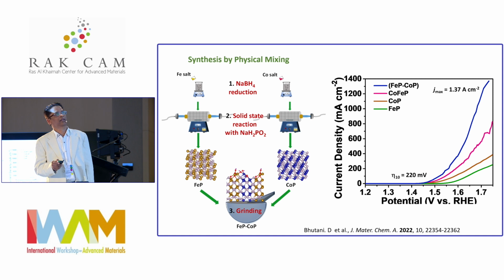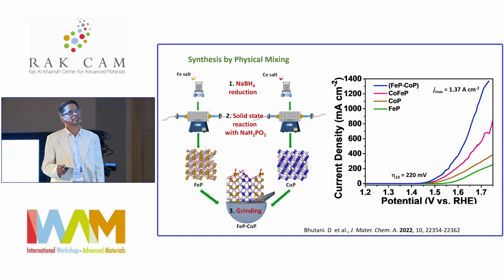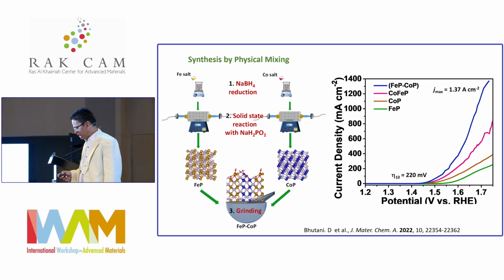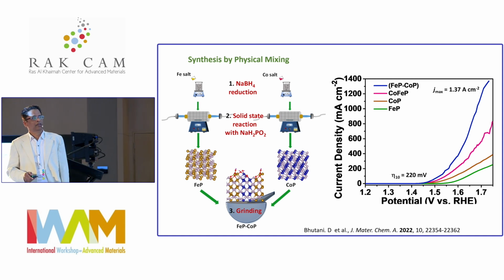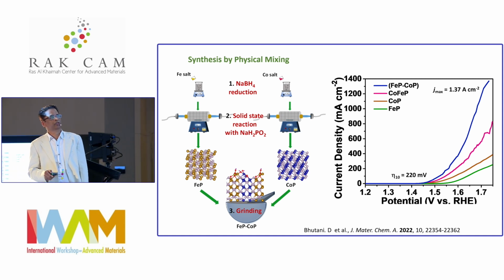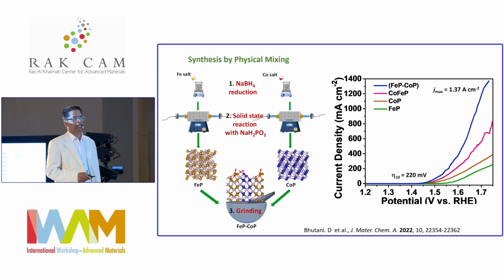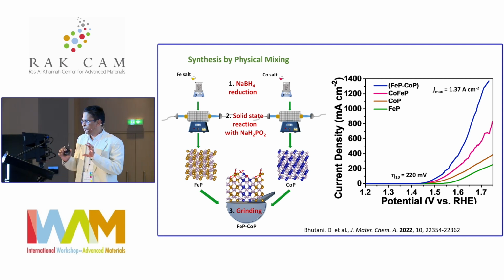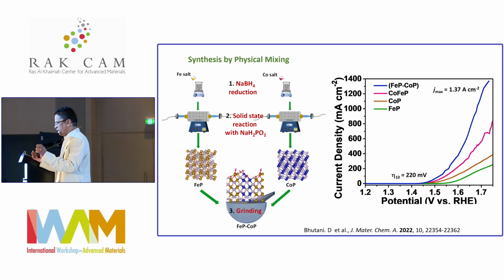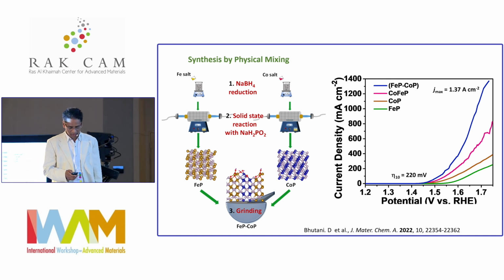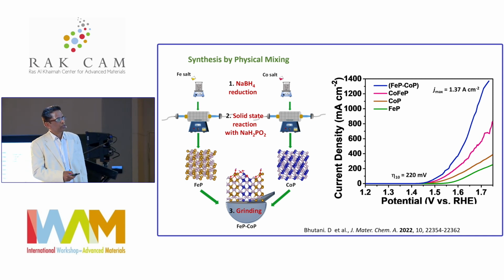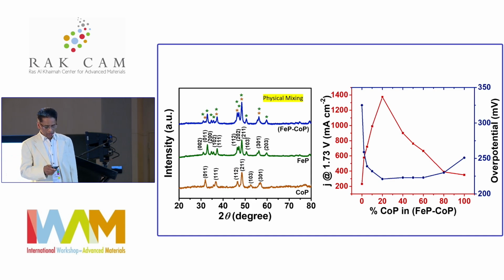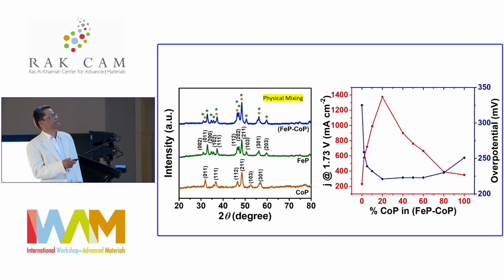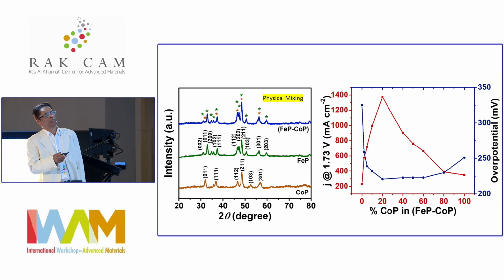You can see that it is very high, almost 1.37 ampere per centimeter square current density at eta 10 of 220 millivolt, a huge reduction in overpotential and a very high enhancement in the activity just by mixing the two phosphide particles separately. So we have looked into that. The best activity comes from the cobalt to iron 0.2 to 0.8 ratio.